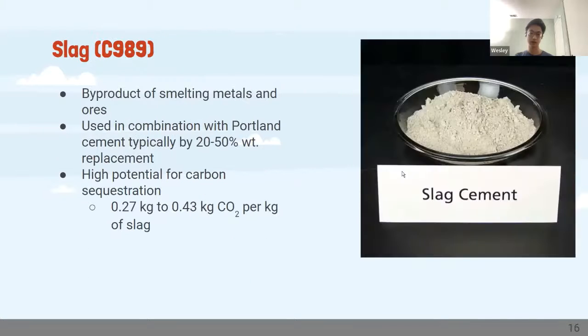But yeah, next slide. So next SCM that I would like to introduce is called slag, and it's essentially a byproduct of smelting metals and ores like iron and steel. So slag is a waste material from the iron and steel industry, and you can actually use it as an SCM to replace Portland cement. And research has shown that you can typically replace Portland cement by up to 20 to 50 weight%.